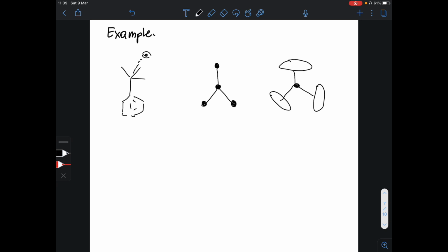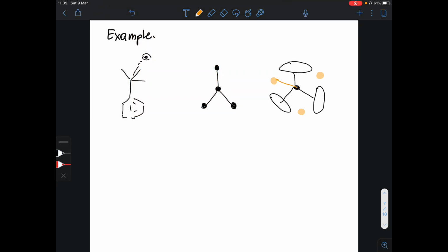And if we refine it, we would also probably see that between these carbon atoms, especially if you work on an isotropic model before making it anisotropic, there are some electron density peaks that are quite high. And these electron density peaks are in fact another orientation of these 3 carbon atoms from the tert-butyl group.